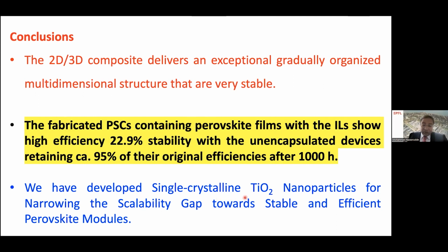So we have developed single crystalline TiO2 nanoparticles that I haven't discussed in more detail. Actually, the purpose of this single crystalline TiO2 nanoparticle is to enhance the conductivity of these materials. As a result, you will see a much enhanced fill factor. All this aspect I have not discussed, but this is the beauty of these single crystalline nanoparticle materials, which increases the conductivity, based on measurements done in Germany by Professor Vladimir. He has done the microwave conductivity measurements of these materials. The conductivity is very high.